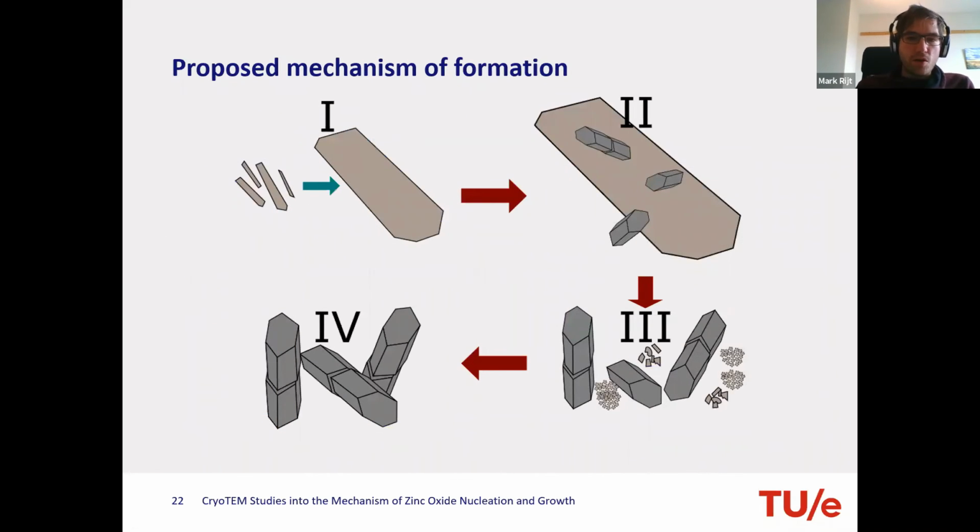Now, so we have this layer basic zinc acetate, zinc oxide. Why does this transition occur? One thing that we hypothesize is that you also see in other crystals that above a certain size of your crystals, you start to introduce a higher probability of defects. And when you have this defect in your crystal, you have the risk of when it's probed by other forces, like for example the stirrer bar underneath in your reaction, that it might break from that point on.